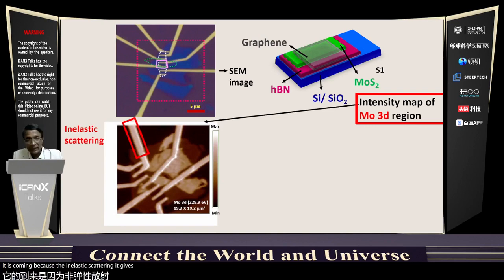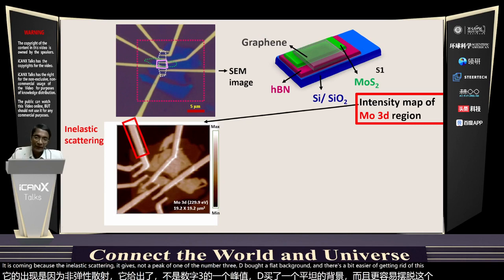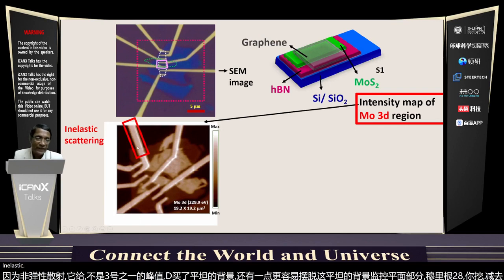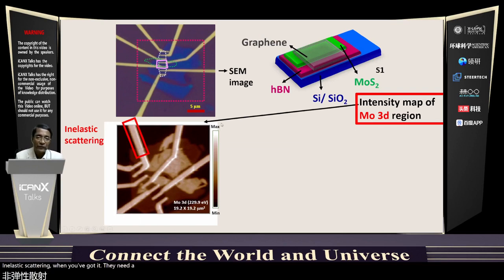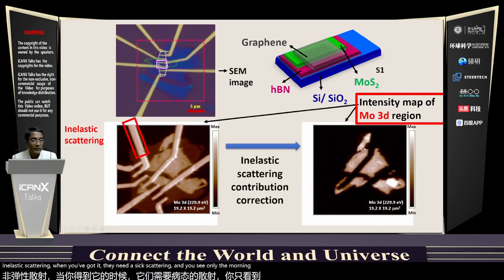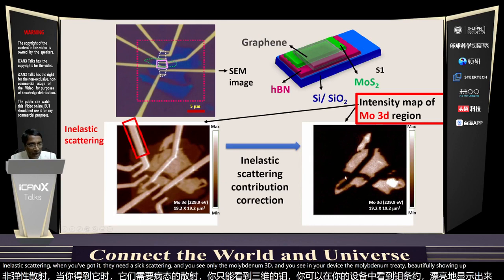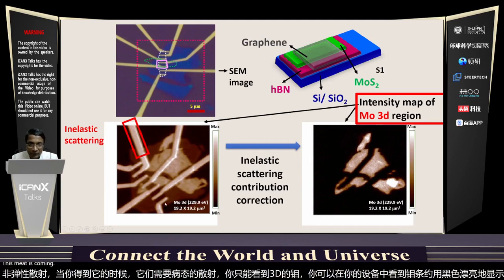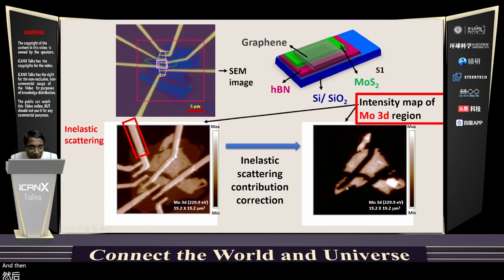It gives not a peak of molybdenum 3d, but a flat background. And there's a very easy way of getting rid of this flat background. So you monitor in the flat part and at the molybdenum 3d peak, and you subtract out this inelastic scattering. When you correct the inelastic scattering, and you see only the molybdenum 3d, and you see in your device the molybdenum 3d beautifully showing up, this black part are these leads that you have seen. So this lead is shadowing this one. This lead is coming from here. And then you can see a little bit of a shadowed part here.